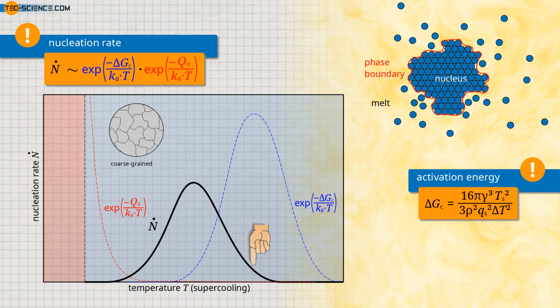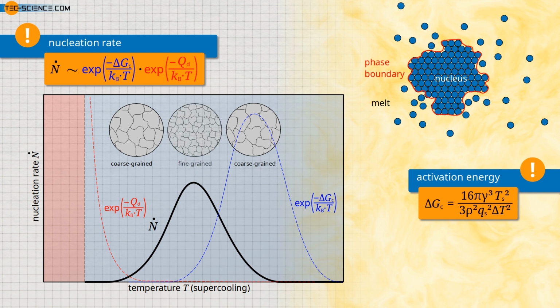If the supercooling is too strong, the situation is similar. Due to the low temperature, the activation energy of diffusion is much greater and now inhibits nucleation, although the activation energy for nucleation would be very low. In turn, only a few grains are formed, which leads to a coarse-grained microstructure. So there is a maximum nucleation rate at a certain supercooling. Obviously, most nuclei can form at this supercooling, resulting in an extremely fine-grained microstructure.